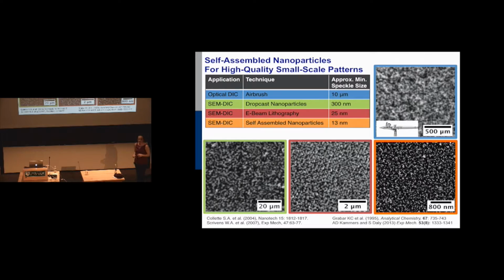The second problem was it was incredibly expensive. The fab fees on that were $1,000 for a sample every time we do it. You can't do that. And the third problem was that you needed a completely flat surface. And we wanted to look at CMCs, which weren't as flat. They were flat, they weren't as flat as we needed. We also wanted to look at crack propagation at the time in CMCs. And if you don't know where the crack's going to go, and you have to use E-beam to pattern everywhere around the sample, it's now a $10,000 sample, right? It's just not feasible. And the pattern wasn't good.